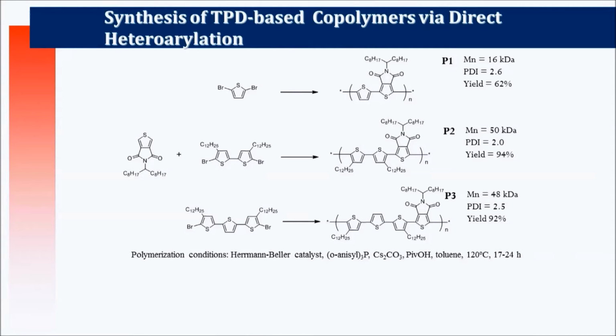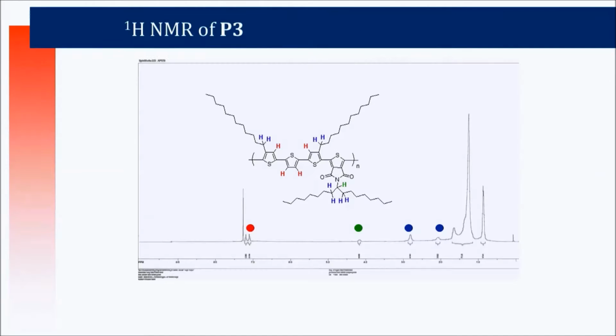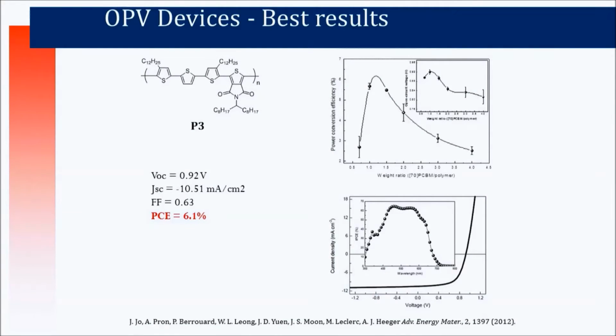So we made a series. We like TPD because, I repeat, there is no problem of selectivity. You just have two CH bonds. So we made different polymers, and we checked by NMR. So well-defined, no defects, alternating, well done, molecular weight about 50,000, which is good in this business. And we sent it to Alan Heeger, the first polymer prepared by direct arylation for solar cell application.